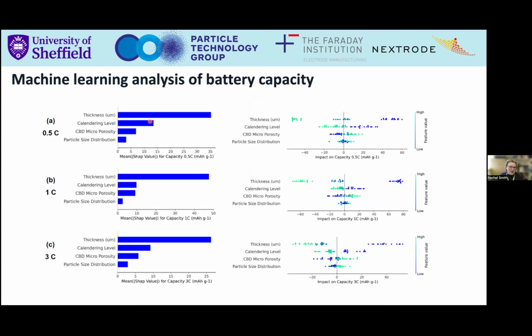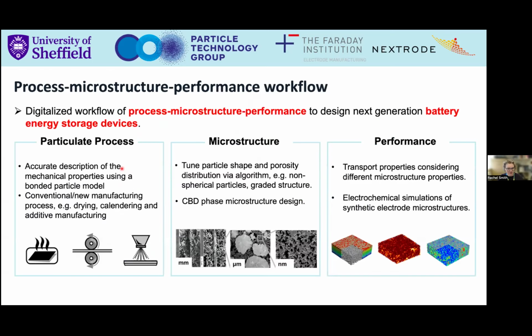So here we're looking at all these different variations: microporosity, our particle size distribution, our calendaring level, and our thickness. The important thing here is that we're able to quantify the contributions of each of these towards our electrode performance. So here we've got this digitized workflow of the process, basically using the process to develop the microstructure and then using the microstructure to develop performance. And we've used the machine learning tools to help us understand this whole relationship even better.